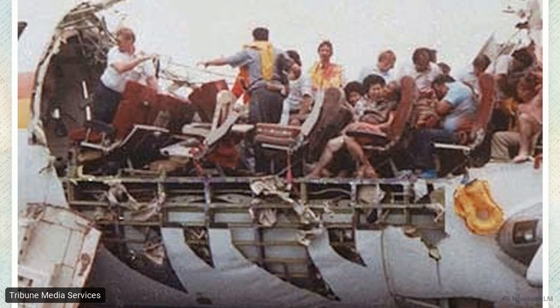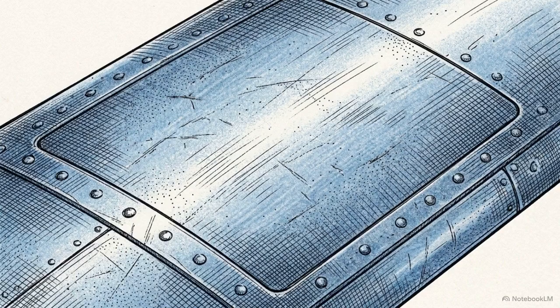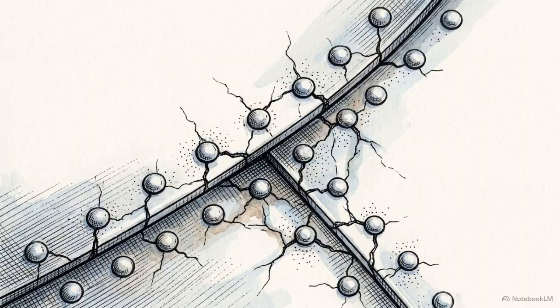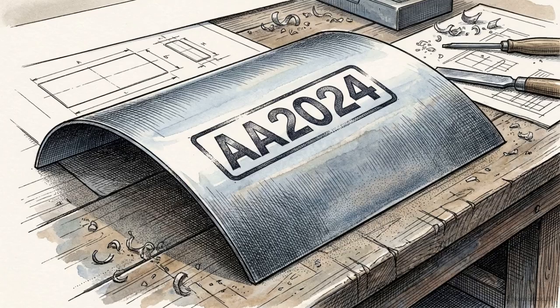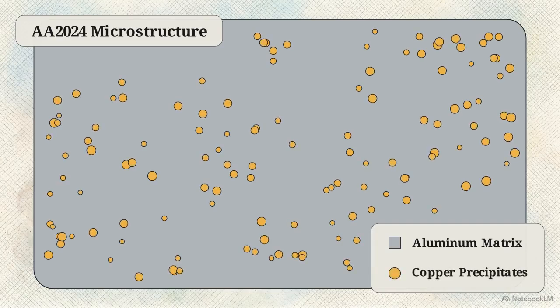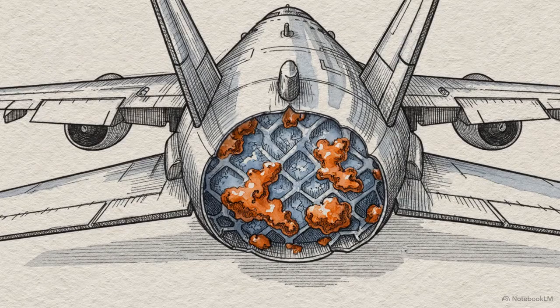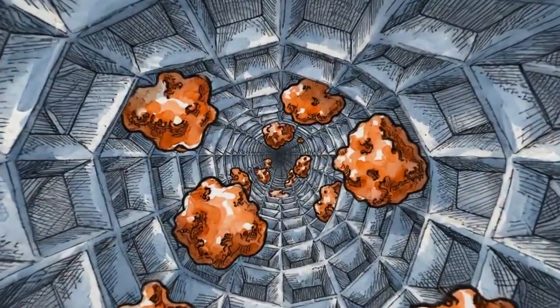In 1988, Aloha Airlines Flight 243 suffered a catastrophic explosive decompression at 24,000 feet. This wasn't a failure of simple physical wear. The structural degradation was caused by multi-site corrosion fatigue, originating inside the rivet lap joints of the fuselage skin. The aircraft was built with AA2024, a high-strength aluminum alloy. To achieve its mechanical properties, the alloy relies on copper-rich intermetallic precipitates distributed throughout the metal. Looking at the bare metal substrate reveals a crystalline microstructure where these copper precipitates are suspended within the aluminum matrix.